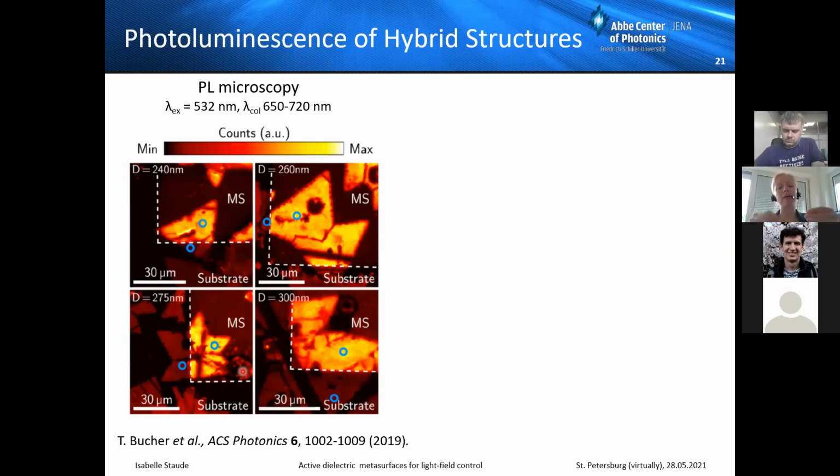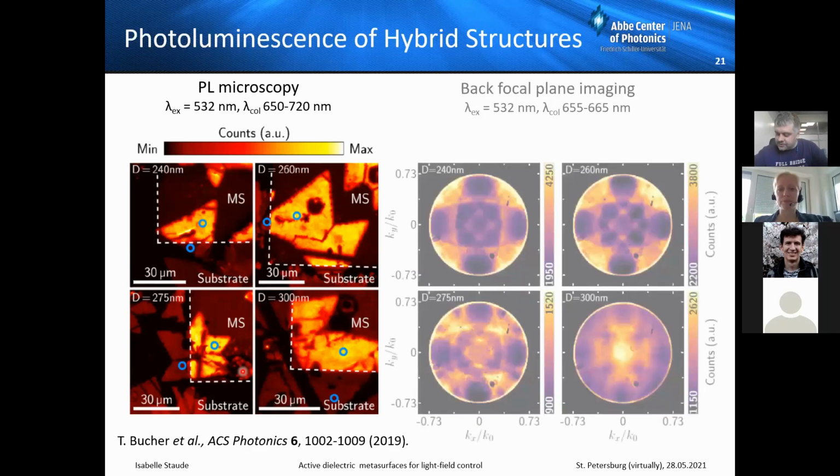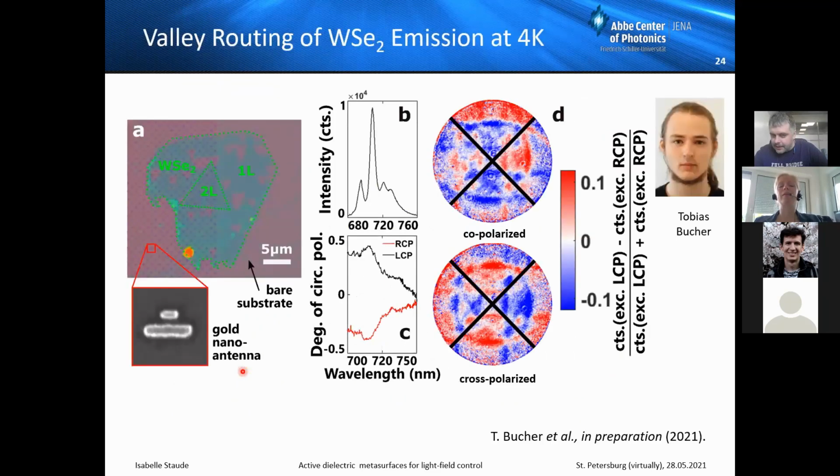And also there is some microscopic strain. You can say this surface is not perfectly smooth, so there will be some residual roughness of this glass slide, and the monolayer will sit on this and experience microscopic strain, which will also quench the photoluminescence to some degree, because some strain can lead to a transition to an indirect band gap locally. But I think the main point was this doping and depletion of the exciton peak towards the trion peak.